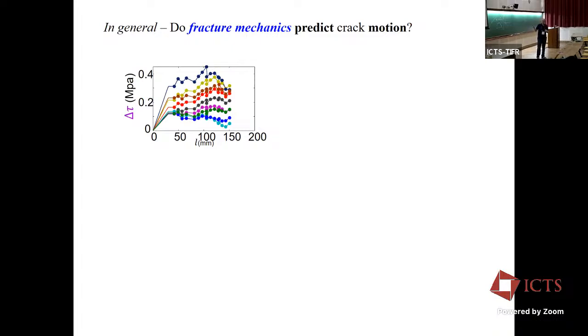Okay, but we took the same two slabs of stuff and we did 10 experiments. Each one we loaded with the same normal force. And we then cranked up the shear force for each one. And for example, it wasn't me, it was my student, Ilias Svetlitsky, but I use the royal we here. When we got to this stress, then we perturbed the back of the system, hit it with a hammer or something, I don't know. And then we watched what happened. So when you perturb the system at this level, then you get an earthquake.